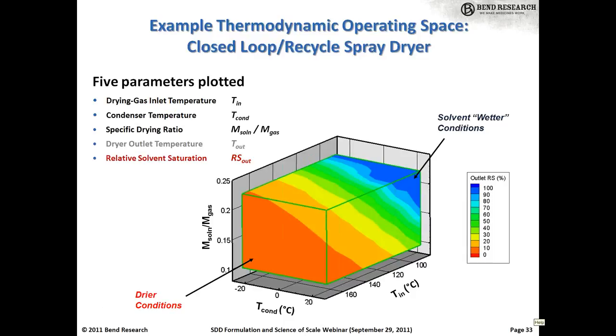You can also plot within the cube, as we did in the 2D case, contours of constant relative solvent saturation. So the wet conditions, or solvent wet conditions, are shown back here in the upper back right, and then the hot or the drier conditions are shown up front.